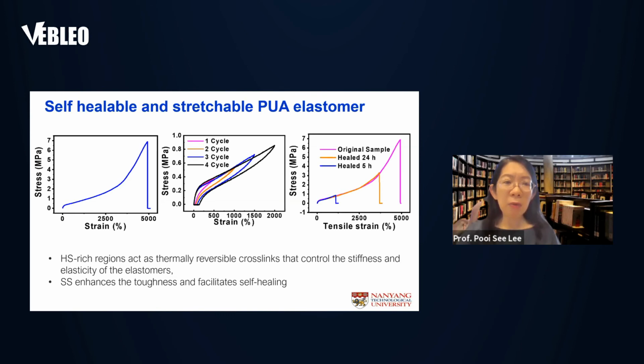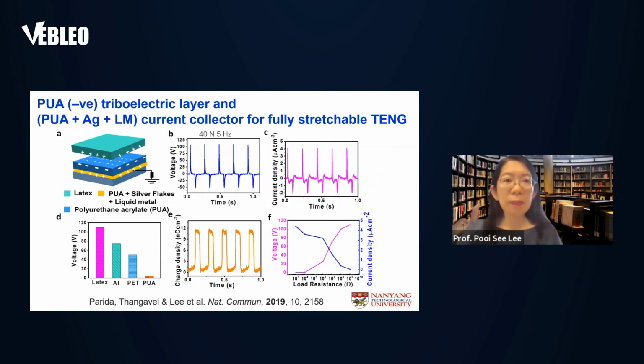And in this polymeric matrix, the hard segment always serves as a thermal reversible crosslink, which controls the stiffness and elasticity, whereas the soft segment will be used to tailor the self-healing property, as I mentioned just now, and it also allows a certain enhancement in the toughness. Using this elastomer and coupled with our liquid metal stretchable conductor, we can actually prepare a fully stretchable triboelectric energy